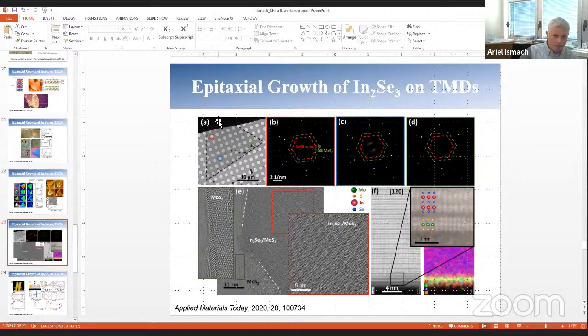So here you can see a single domain of MoS2, which is coated with a few layers of indium selenide. And here, the diffraction peaks, all of them confirm the epitaxial relation. And then, of course, you can have in-plane atomic resolution showing the superstructure of these 2-dimensional layers. And finally, the cross-section shows very clearly the single-layer MoS2 and the multi-layer indium selenide, in this case really thick, on top of the MoS2. So by all this, we can prove that it is indeed growing epitaxially.